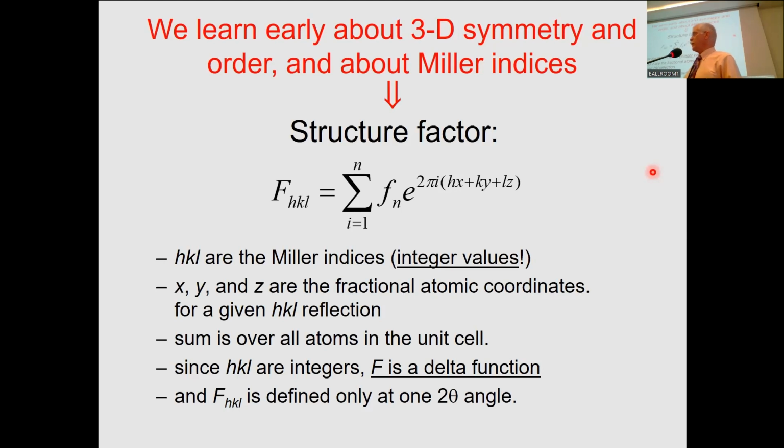And from that, we learn about something called the structure factor, which is important whenever we're interested in crystal structures, calculating diffraction patterns, intensities of diffraction peaks. The structure factor is related to the intensity, but the important thing is that the structure factor is for each individual reflection in an X-ray diffraction pattern. And we define those reflections based on their HKL values, their Miller indices.